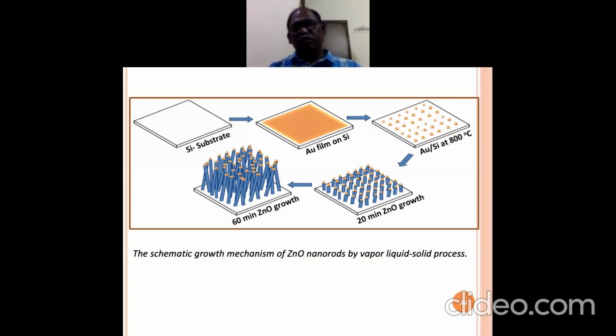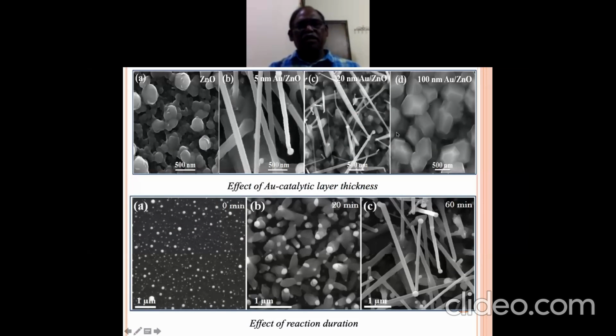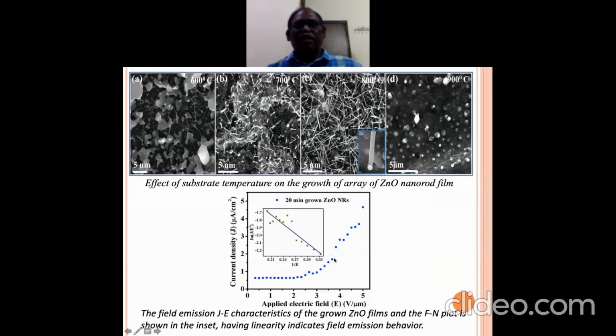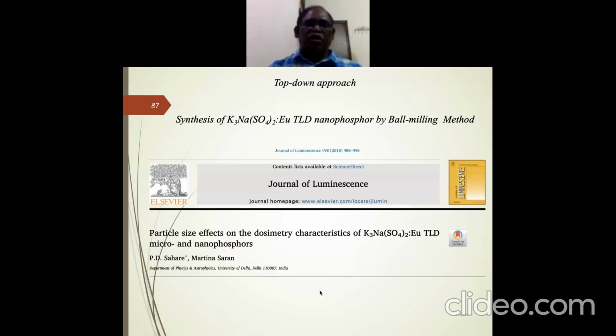But then you have to monitor the thickness of this gold film, the reaction duration, and the substrate also. But we have found that there is a good current density of field emission, and this material or this film can be used for field emission applications. So I will not go into all the other things, like ball milling and all that.